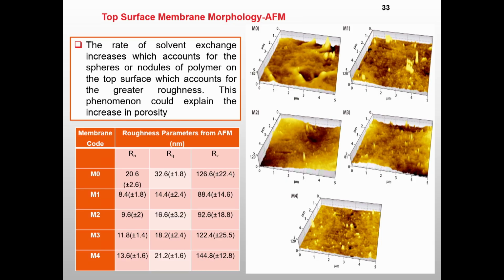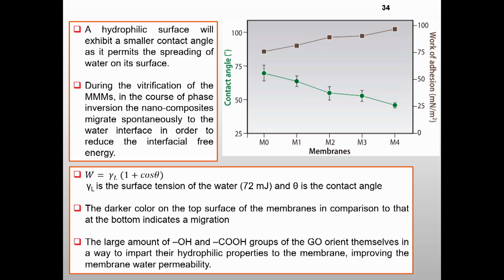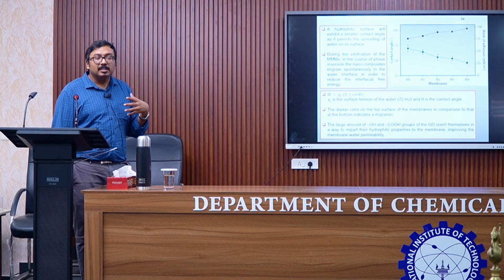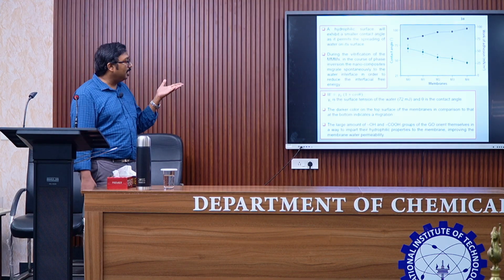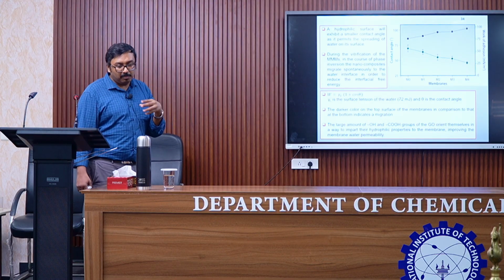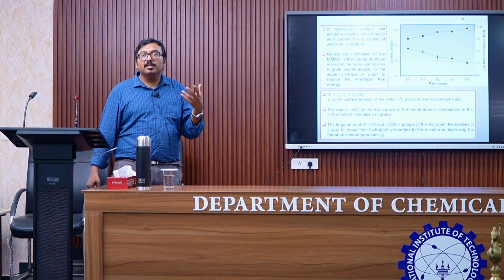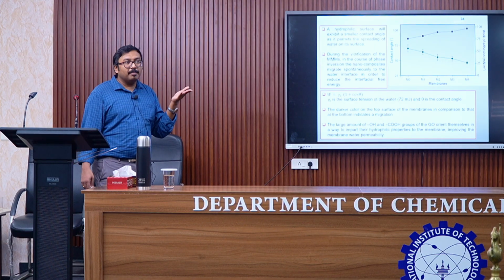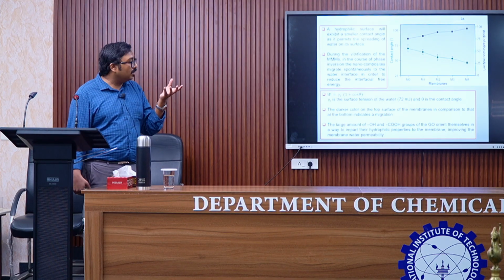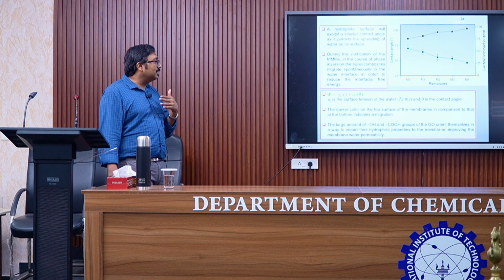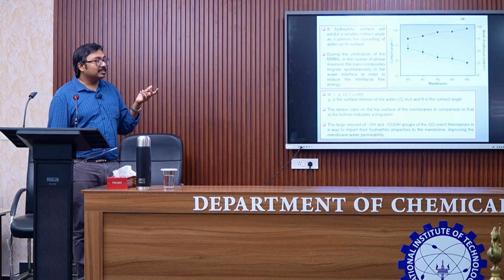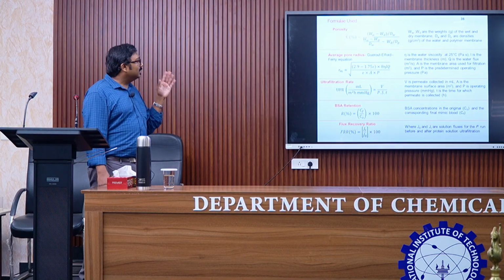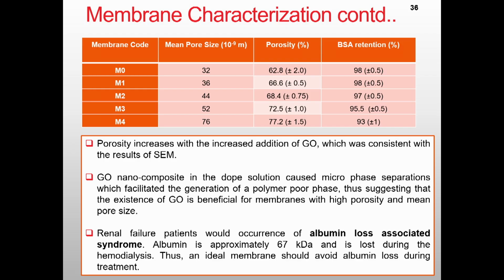And in the AFM images also, there were changes in the membrane roughness when we used graphene oxide, as well as the contact angle. Contact angle is a direct indicator of the hydrophilicity of a membrane. If you have water dropped on a surface, we measure how much it spreads. The more it spreads, the more affinity water has with the surface. Blood is mostly water, and since the membrane is more hydrophilic, membranes in contact with blood would have the least adverse effects compared to the more hydrophobic surfaces. These are some of the formulas that were used to calculate all these parameters.